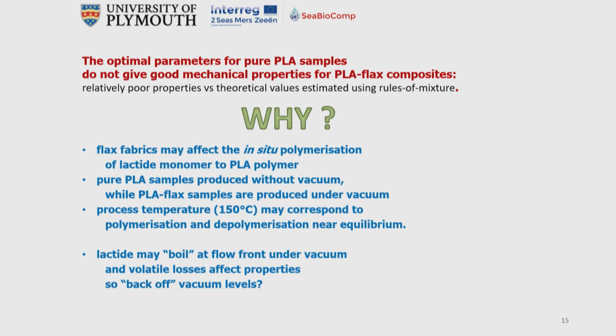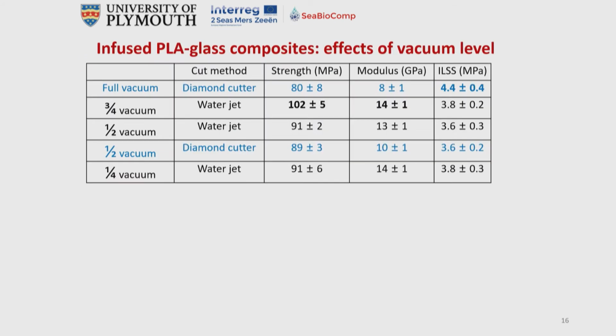Pure PLA samples were produced without vacuum, while the composite samples were produced under vacuum, because that's the nature of the infusion process. We think there may be a polymerization, depolymerization equilibrium around the process temperature we've been using. And lactide may boil at the flow front under vacuum, and the volatile losses affect the properties. So we looked at backing off the vacuum levels, and it does look like lower vacuum produces better properties.